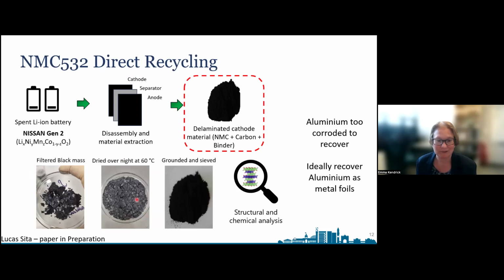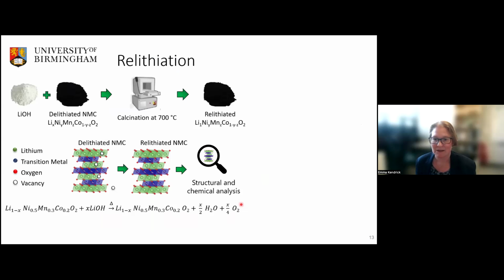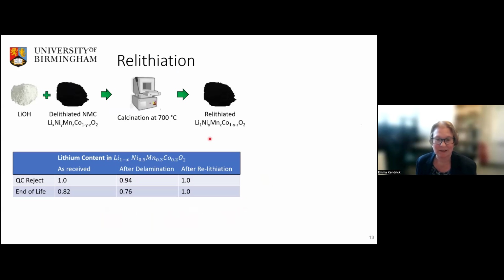In this case, we were able to recover quite nice pieces of the cathode, grind it up into a powder, and then analyze the quantity of elements in here. In this case, we actually had very pure samples with very little aluminium or copper impurities. And by a simple relithiation process, just using a lithium source such as lithium hydroxide or lithium carbonate, we could actually relithiate this 532 material from what was the QC rejected and the end of life.